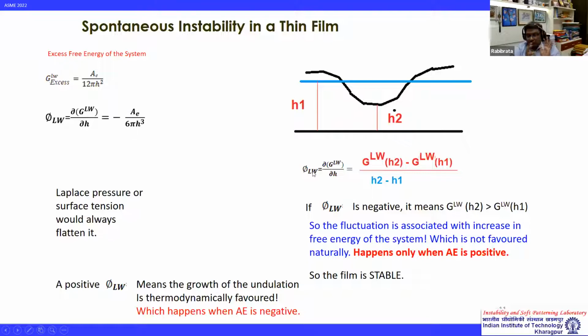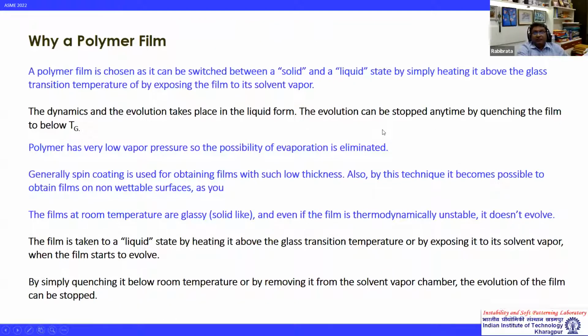So what I mean to say, in simple terms, is that if the interfacial interaction between the free surface and the substrate-film interface is attractive, and if the strength of it is higher than the stabilizing influence of surface tension, then these fluctuations may not subside in an ultra-thin film and can grow with time. And if this fluctuation grows, then what is going to happen? Eventually the amplitude of this growing fluctuation matches the film thickness, and the two separate interfaces eventually merge, forming a hole.